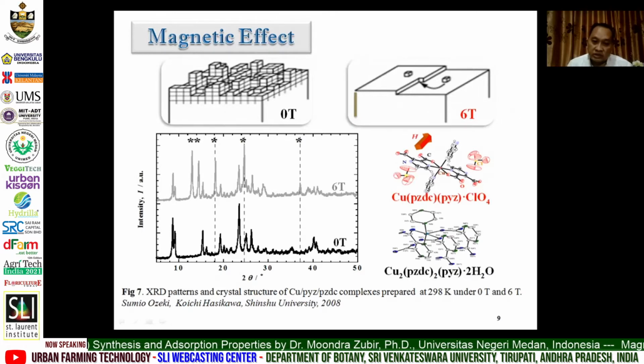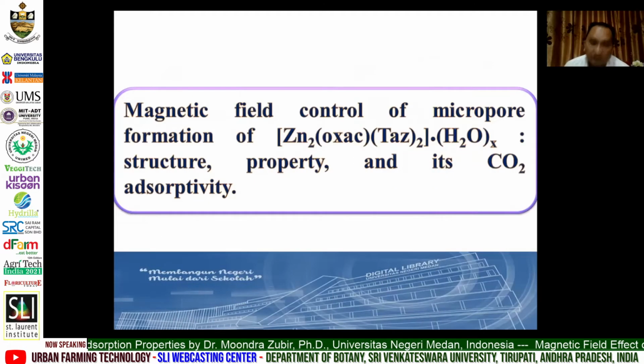Previously, at Shinshu University, Japan, in 2008, they successfully prepared one PCP, Cu PZDC PYZ. When prepared at 0 Tesla, this PCP forms as a 5 coordination number PCP, and then changes to a 6 coordination number when prepared in a 6 Tesla magnetic field. So in this experiment, I observe how the magnetic field controls the micropore formation of zinc oxalate TAZ 2 water. In this first PCP we use TAZ with water as the solvent, and we observe the magnetic field effect on structure, properties, and also adsorption.